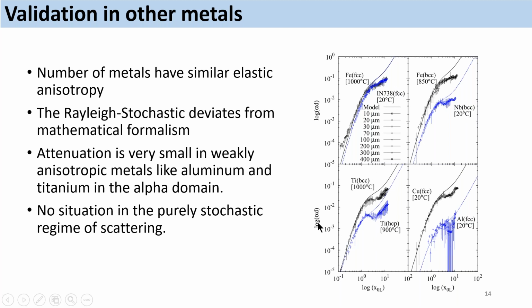What I want to show in this slide is that it's not easy to measure grain size in all materials the same way. The reason is that the attenuation will not be as intense in some materials which are weakly anisotropic, such as aluminum. So it's usually very difficult to access a measurement of grain size in aluminum, when it is very easy to measure grain size in nickel, in austenite, like I said, and in titanium BCC, for instance.